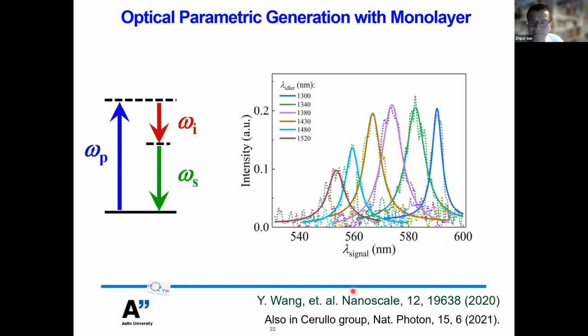We also tried parametric generation with the monolayer MoS2. This parametric generation process is the most common way to generate light at a new frequency. This figure shows what we get with the monolayer MoS2 device. You can see here we are able to generate tunable pulses across a broad spectrum range from 1550 nanometer to around 600 nanometer. This tuning range is mainly limited by our pump laser source. It's not limited by our monolayer material, but by the experimental setup.